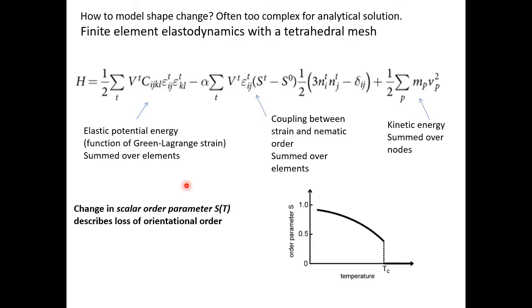And so, for instance, in each element, we can define a mechanical strain that tells me how much it's been stretched. So if I know the positions of the tetrahedron in the unstretched state, and then I deform it and I've moved those particles, I can calculate the strain from the after to the before, right? The difference, those displacements. And epsilon ij is a strain tensor that defines the amount the material's been stretched. Okay, it's a tensor. That's why you see all this IJKL stuff.